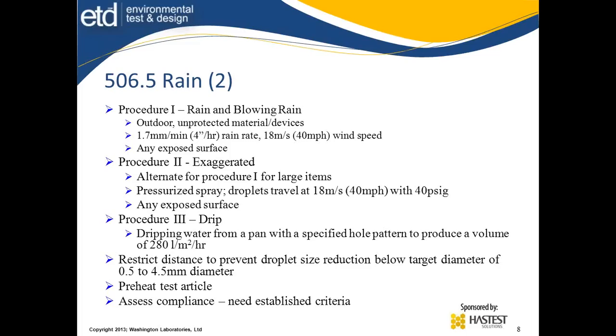Procedure 3, the drip test, or dripping water from a pan with a specified hole pattern. It produces a volume of water of 280 liters per square meter per hour. You need to restrict the distance when you're doing these blowing rains, especially to prevent droplet size reduction below the target diameter. If you have a long distance, they tend to expand out and become smaller drops, so you need to get that droplet size taken care of.